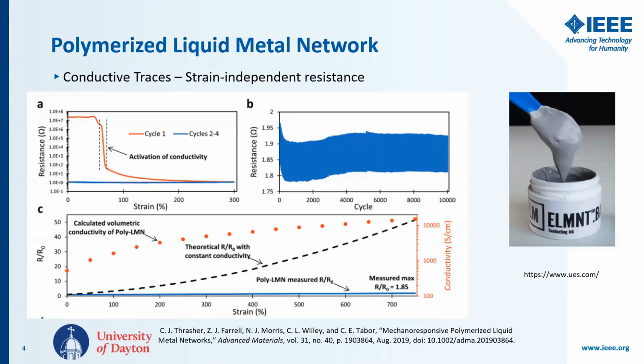When it is strained, there is very little change in resistance, with an R over R naught not exceeding 1.85, normalized resistance, up to 700% strain. So this is a very strain-tolerant conductor.